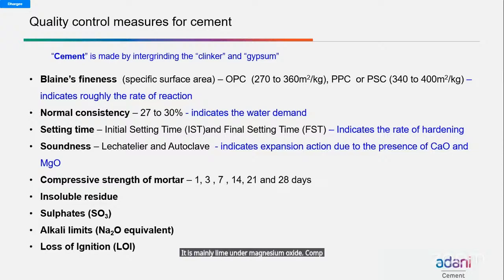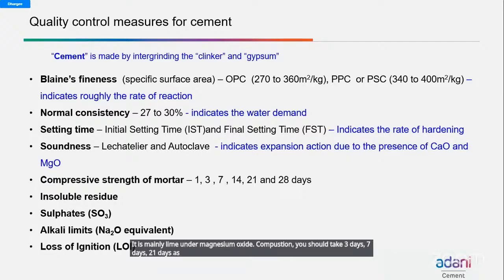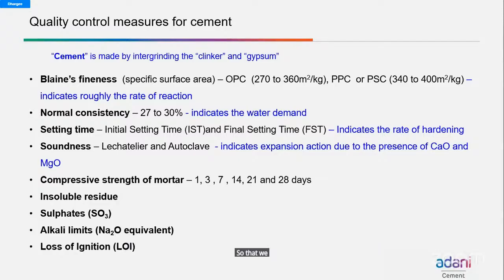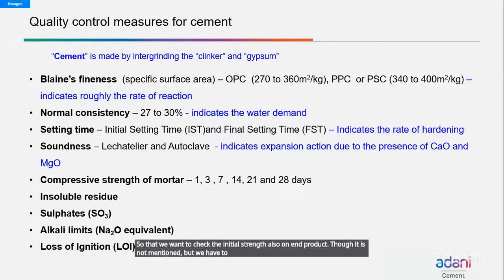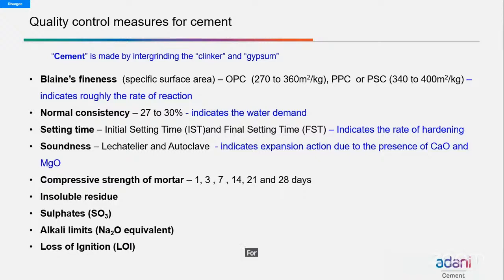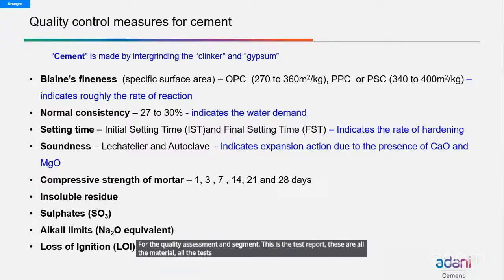Compressive strength, we check at 3 days, 7 days, 28 days as per IS norms, whereas we check 1 day, 3 days, 7 days, 14 days, 21 days, even 28 days. We check our cement strength. Why? Because today we manufacture cement, tomorrow it comes to the market. So we want to check the initial strength also on the end product. Though it is not mentioned in IS norms, we have to understand what the strength is before we use it. And insoluble residue, sulfate, alkali limits, and Loss of Ignition, we take all of these for the quality assessment of cement. This is the test report. These are all the tests you normally get in your test reports.